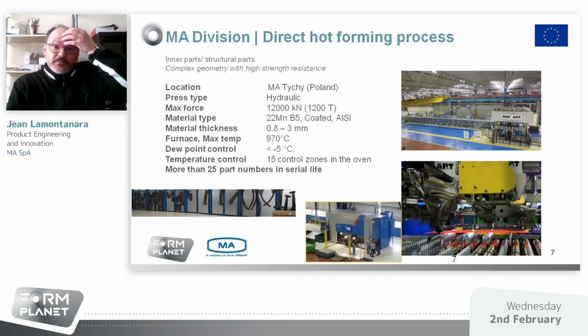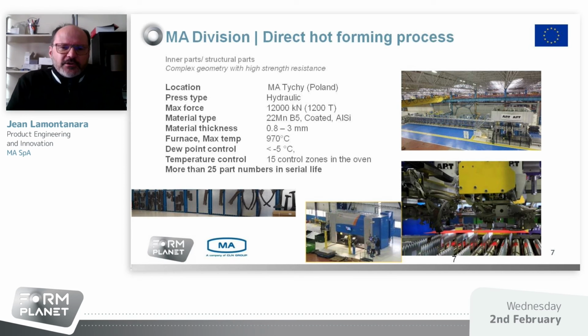So some features about the hot forming. We have a hydraulic press, about 1,200 kilonewton power. We can process all kinds of 22MnB5 coated, so aluminum silicon, meaning what are well known as Usibor 1500 megapascal, also Usibor 2000, and so on, for the range of material thickness from 0.7, 0.8 to 3 millimeters. The furnace is a furnace with 15 control zones, and we have a dew point control that we can guarantee less than -5 degrees. And I will go in detail about the dew point control. And right now, we are producing more than 25 part numbers in serial life, mainly for Stellantis, so ex-FCA and ex-Peugeot.